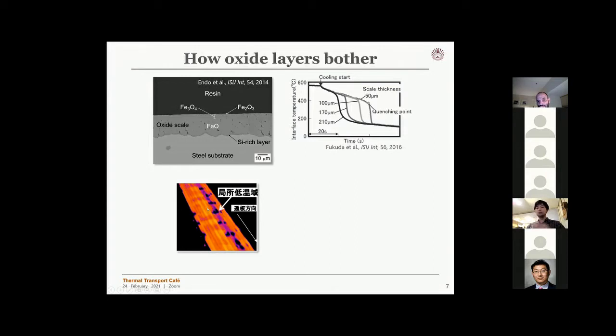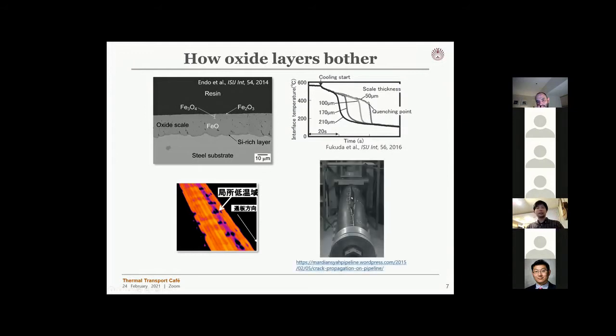If you have this non-uniform cooling profile over the surface, the material will accumulate residual stress, and the residual stress will cause cracking or some catastrophic failure. So we don't want this.